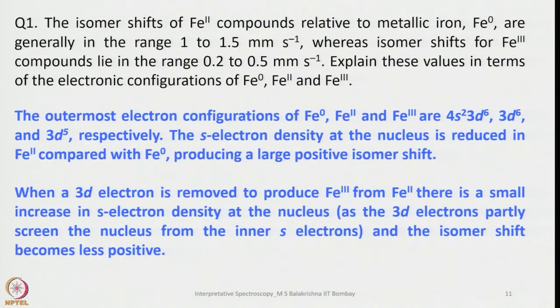So the isomer shifts of iron 2 compounds relative to metallic iron Fe0 are generally in the range of 1 to 1.5 millimeters per second, whereas isomer shifts for iron 3 compounds lie in the range of 0.2 to 0.5 millimeters per second. So, explain these values in terms of the electronic configuration of iron 0, iron 2 and iron 3. So, this is a question. I read out again: the isomer shifts of iron 2 compounds relative to metallic iron Fe0 are generally in the range of 1 to 1.5 millimeters per second, whereas isomer shifts for Fe3 compounds lie in the range of 0.2 to 0.5 millimeters per second.